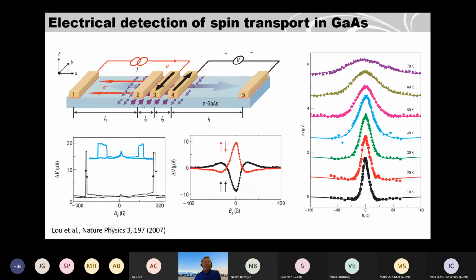So what people have done is a similar device to the one I showed you for the metallic spintronic case. They have an injector here and a detector. It's gallium arsenide. Injector and detector are ferromagnets like iron here. And depending on the magnetization of the injector and detector, what you see is the spin valve signals, and this is hysteretic. And in the middle of this signal, you see a peak-like structure. This is a magnified version of this signal here. I won't go into the details, but it is coming from nuclear spin interaction. You create this spin polarization in the gallium arsenide, and your spins stay polarized for a longer time because of the nuclear spins. It's called dynamical nuclear polarization. So your electrons around this nuclear spin can stay a bit longer.